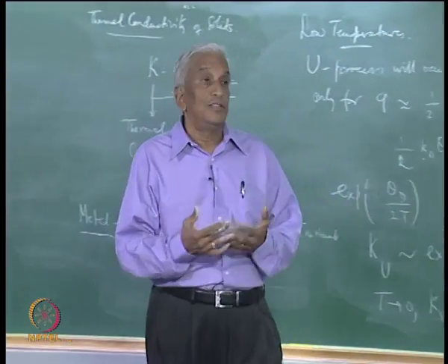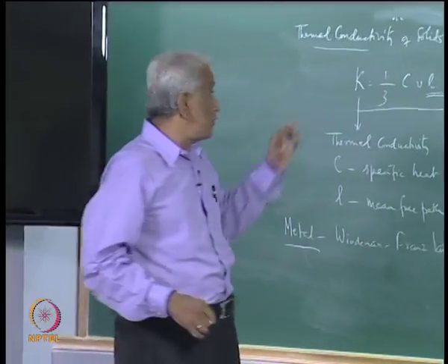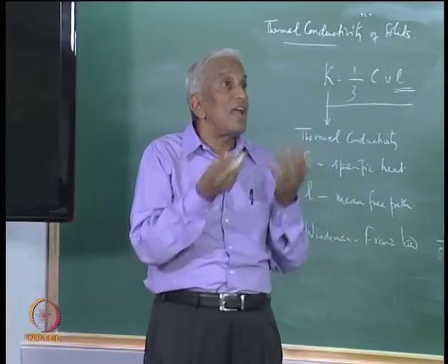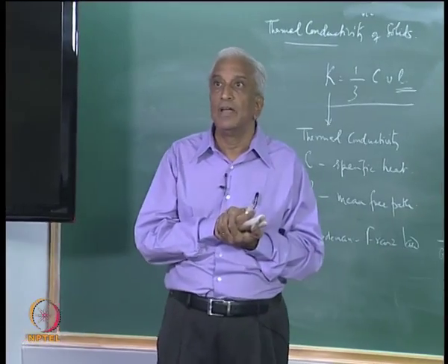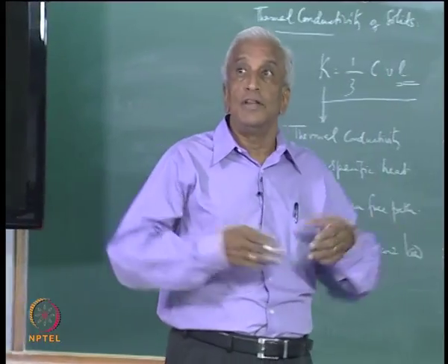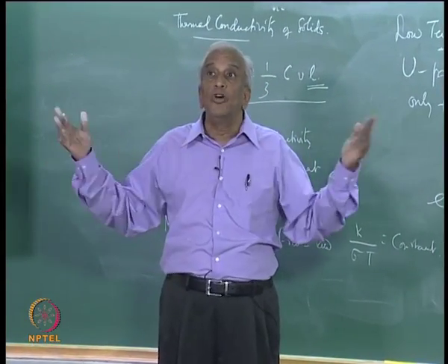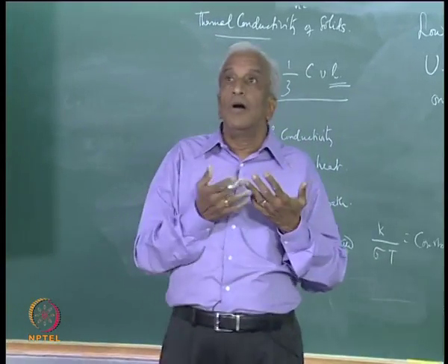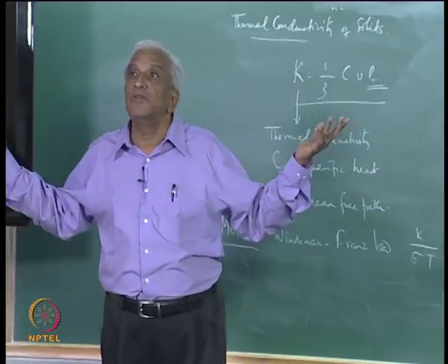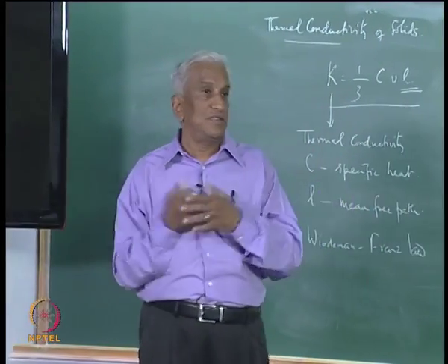But the total thermal conductivity will not go to infinity, because it is limited by contributions from the boundary and impurity scattering. At low temperatures, the boundary scattering will dominate. For a pure crystal, the mean free path of phonons is nearly equal to the dimension of the crystal, because the phonons have no impurities or defects. It becomes very large, so it will become practically independent of the temperature.